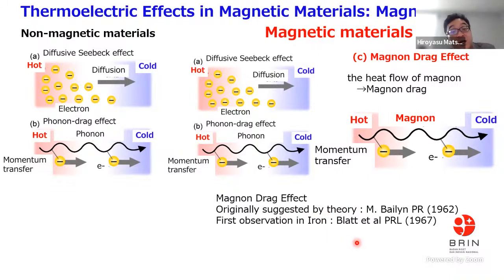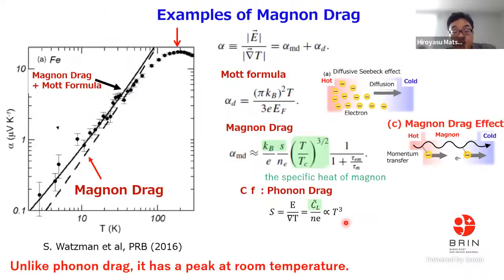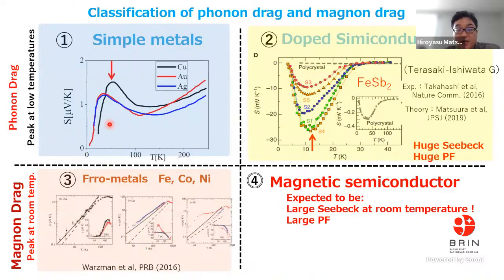This is partly observed by Blatt. So this is an experimental result for the iron case. Yesterday I talked about this. This black point is the experimental result, this line is the magnon drag effect, and this solid line is magnon drag plus the Mott formula. The Mott formula is coming from the diffusive effect. So it is very consistent. This one is coming from the magnon drag.